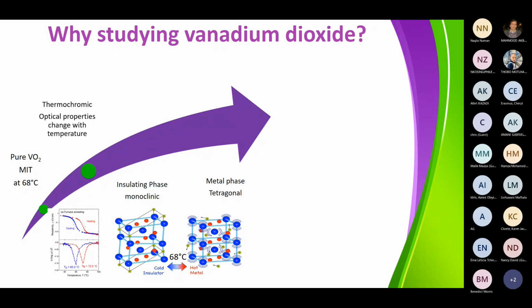If you look at how this material is interesting, you will find that the optical properties are also changing with temperature. This is quite interesting, especially because it has a thermochromic property that is extremely useful for doing, for instance, smart windows. The other thing that people have been observing is that you can change this transition temperature of 68 degrees Celsius by doping with other materials. You can put donors like tungsten 6+, or acceptors like chromium 3+, and this is going to change the transition temperature. So you can either increase or decrease the transition temperature by doping VO2.